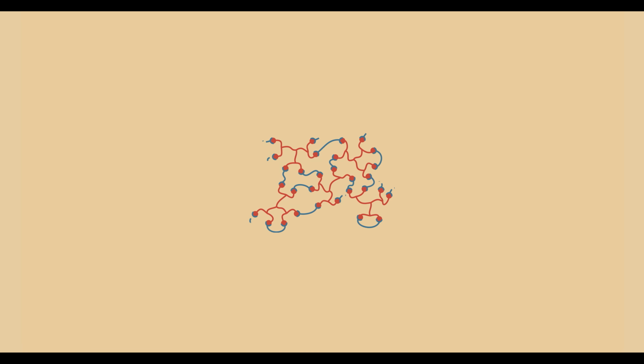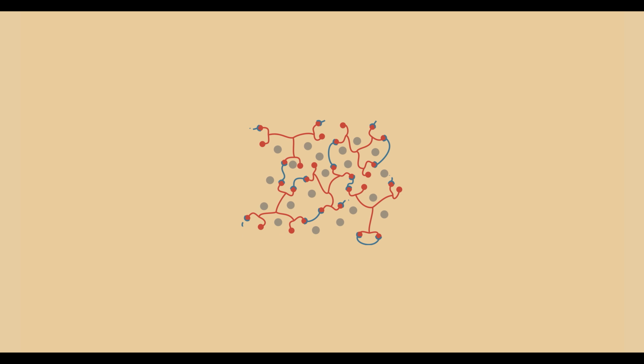Just as we fuse layers together during printing, we can also fuse different self-healing materials. Materials with different mechanical properties can be obtained by adjusting network design parameters like stoichiometry, spacer length, or by incorporating fillers into the network. But why would we do this? Well, the ability to seamlessly integrate multiple materials makes it possible to create more complex robot designs and to enhance their functionality. One of these crucial functionalities that we can introduce is sensors.